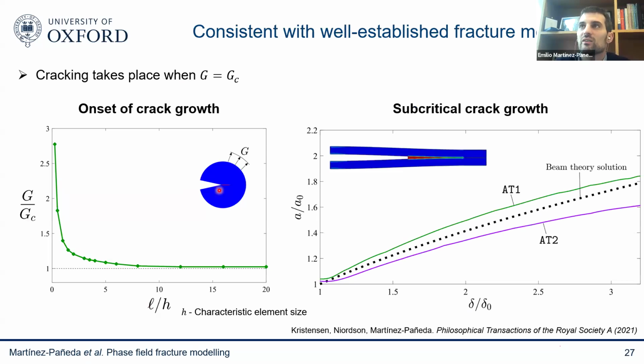We also check that this is correct not only for initiating a crack, but also for propagating a crack. So you can go here, we applied a remote K field or J field using the Williams expansion. Here we use a double cantilever beam. So it's a problem where we have an analytical solution using Timoshenko's beam theory to predict the energy release rate. So we can plot crack extension versus applied displacement. And we can see that again, we're in good agreement. And that is one key element here. So that is good news.